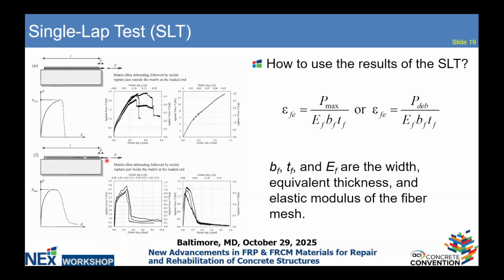So how do you design? Well, you take your Pmax or Pdeb. You see two symbols because we need to understand if there is a cohesive failure, so there is a plateau, or there is a simple max. But basically, you take a maximum value of your load from a single lap test, and then you divide it by the elastic modulus and the area of the fibers to get your strain. So there is no additional work on the response of the single lap test. And again, it's because at the crack cross-section, the fibers are the ones acting.